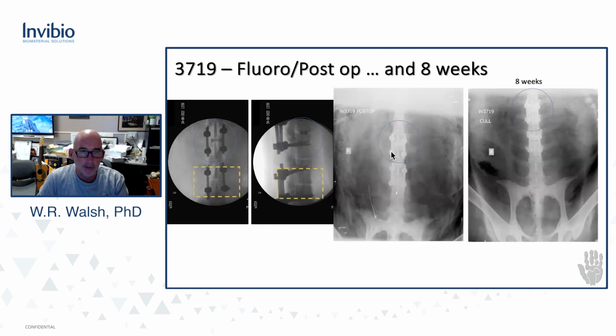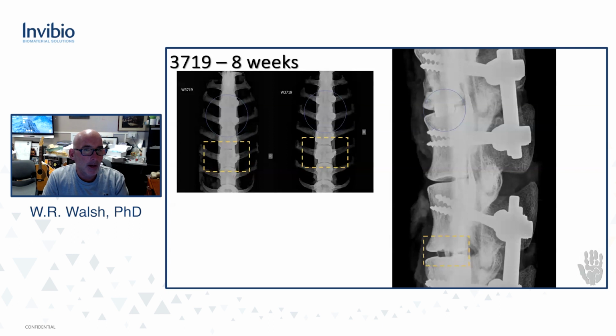All we can really see is that we have a block of metal there. We can't see the PEEK, and we can tell that the screws are relatively stable, no loose screws in the study. Then we look at Faxitron radiographs where we harvest the spine and we have a slower exposure, longer X-ray detail. We really don't know what's happening in the PEEK, in the titanium, but we can see a bridge of bone in the PEEK.